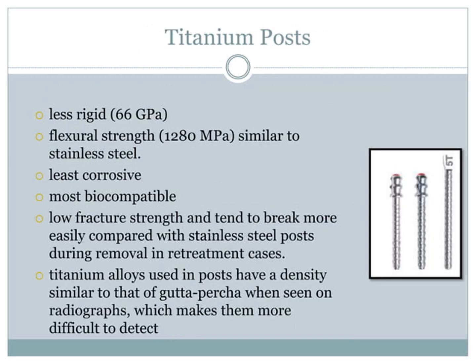Titanium posts are less rigid. Flexural strength is similar to the stainless steel, less corrosive, most biocompatible, low fracture strength, and tend to break more when compared to the stainless steel post during the removal and the retreatment cases. Titanium alloys used in the posts have a density similar to that of gutta-percha when seen on the radiograph, which makes them more difficult to detect.